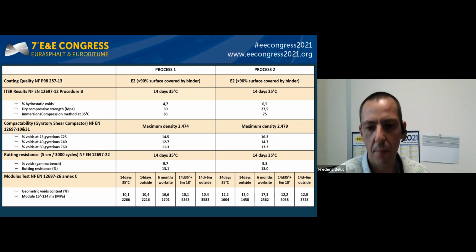Finally, the elasticity moduli we measured are fairly low and typical of emulsion mixes, with values of between 1,500 and 5,000 MPa, depending on the aging conditions. First, 14 days at 35 degrees. Second, 14 days outside. Third, core samples taken from the site after 6 months. 14 days at 35 degrees plus 6 months at 18 degrees. And the last, 14 days outside plus 6 months outside.